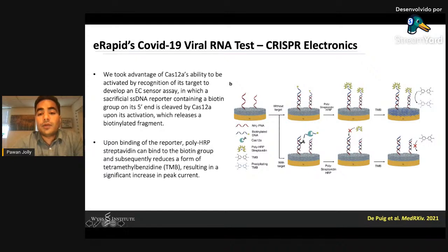So when you have the reporter DNA bound to the surface, you actually see the signal of our substrate through an enzymatic reaction. But if you have the target, the CRISPR cuts the reporter DNA, and therefore you don't have the enzyme that can bind to the surface and you don't have any reaction. So in principle, if you have the target, you're not going to see the signal. If you don't have the target, you're going to see the signal.